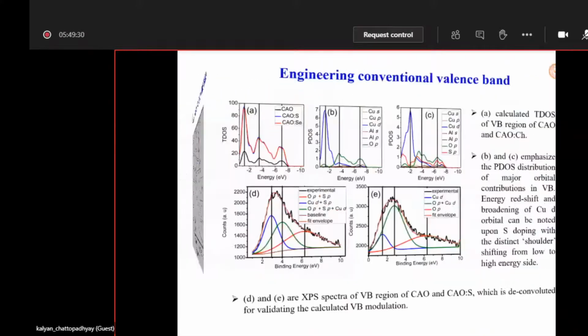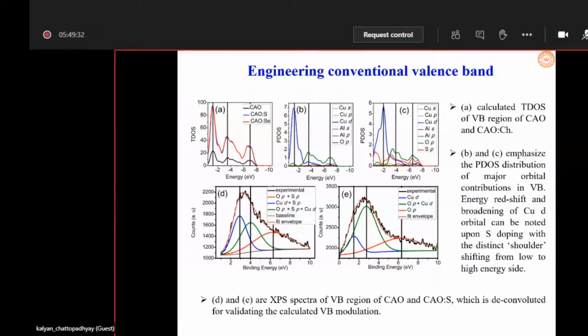Now, to judge the valence band dispersion, we have to place the two results, that is what is predicted from density functional theory based calculation, and also the XPS side by side. I again spend 1 or 2 minutes on this slide. For example, the uppermost panel indicates the density of states. This is the total density of states plot for the 3 samples. This is the pristine one, this is the sulfur incorporated one, the selenium incorporated one, and these are the partial